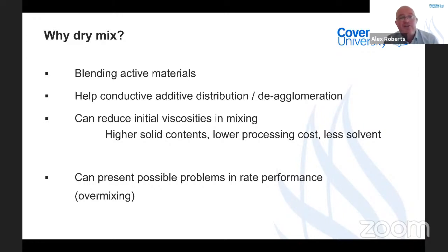So it gives advantages that you can blend your active materials together and you can help with your distribution and deagglomeration of your conductive additives such as carbon black. It can also help reduce the viscosities you get in the mixing, so allow you to get higher solid contents and lower processing costs. But the one thing you must be careful of is overmixing. And this is common to all of the mixing technologies, but can be more of an issue with the dry mix.